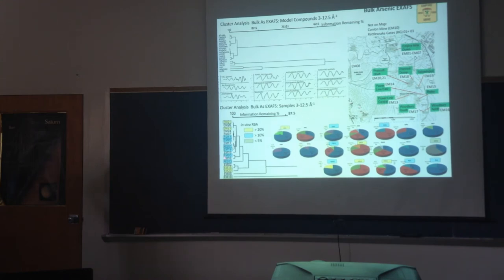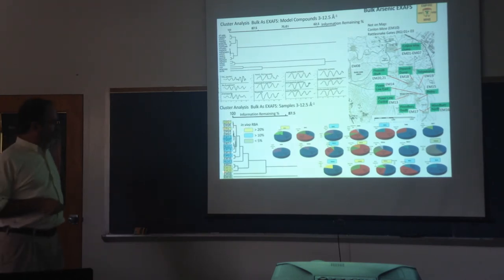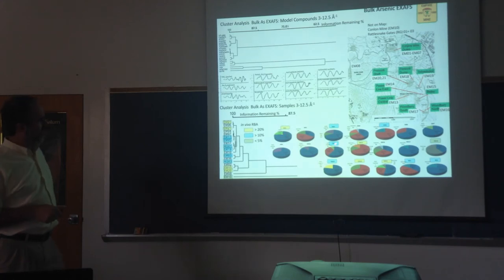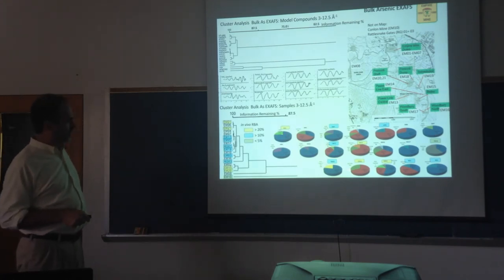And Andrea Foster has used cluster analysis here to see which ones are similar to each other in terms of these characteristics. And she's shown that, for example, EM1 and EM21, which happen to be among the highest in bioavailability, in vivo relative bioavailability, that's the pig study, which is, again, the gold standard for bioavailable arsenic. The four samples that really stand out are shown in yellow, and they tend to have similar mineralogy to each other.